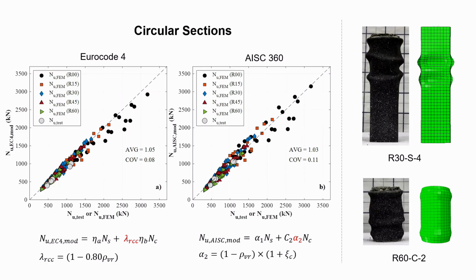And we did the same as well for the concrete-filled steel tubes. Here I'm showing the results for the circular sections. We compared the axial capacity prediction equations in Eurocode 4 as well as the American code. So on the x-axis I'm plotting the experimental results, or the finite element modeling results, the axial capacity against the modified code equations. We had to modify the code equations just to account for the effect of rubber on confinement and to get good accuracy of the results.